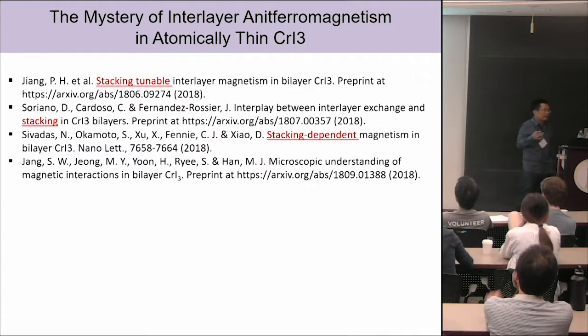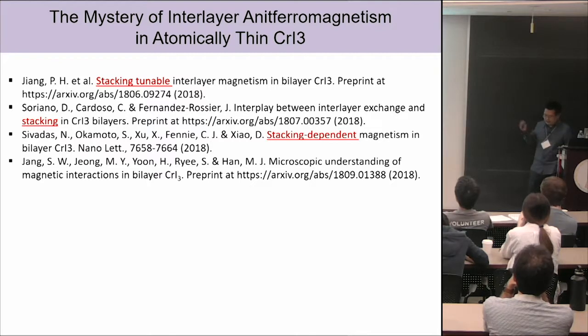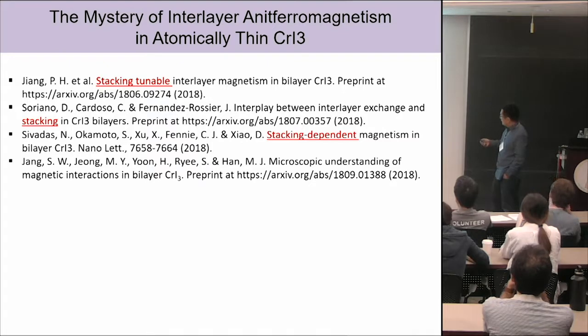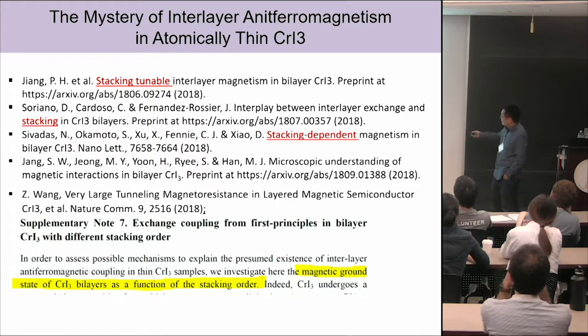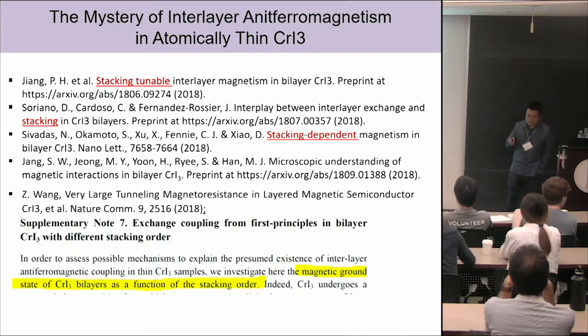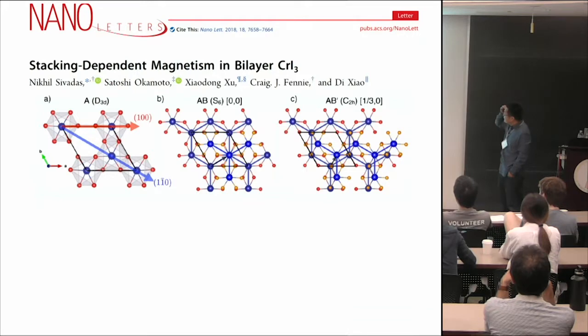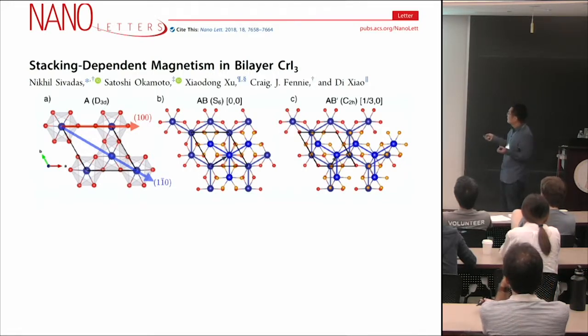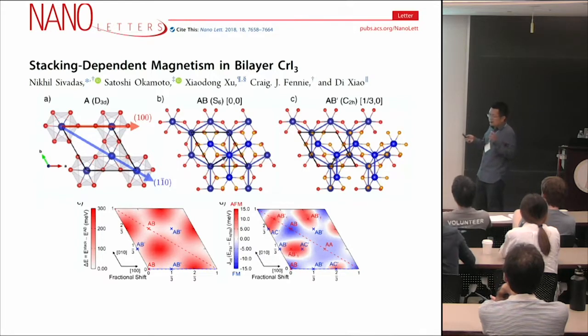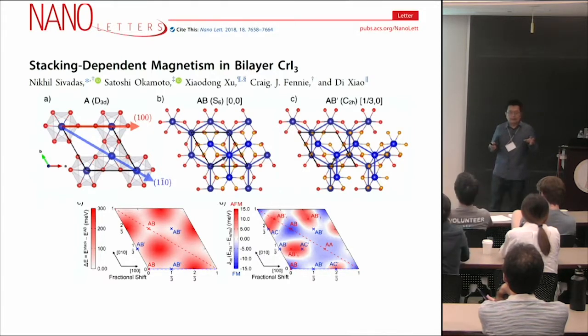In the last couple of years, there's been quite a bit of theory work, and in this theoretical work you see these keywords: stacking. Another work also discusses, in the supplementary, the impact of stacking on the magnetic orders. To summarize the key concept, for these crystals the calculation shows there could be two stable stacking orders. One is rhombohedral, called AB. The other is monoclinic, AB prime. For the rhombohedral, we get ferromagnetic order. But for the monoclinic stacking, we get antiferromagnetic interlayer coupling.